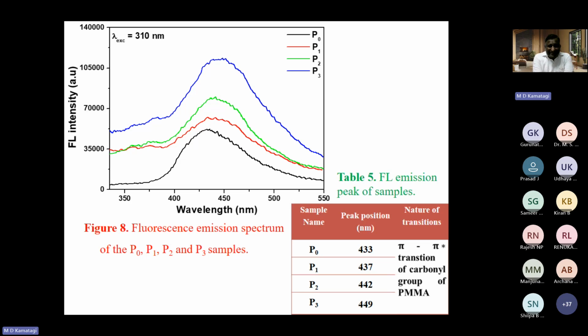The one with the blue line is for the P3 sample, which exhibits a much higher photoluminescence. The intensity of photoluminescence is much more than that of the pure PMMA. Also, there is a shift in the peak values of PMMA. This is attributed to an interaction of ZrO2 nanoparticles with the carbonyl group of PMMA.